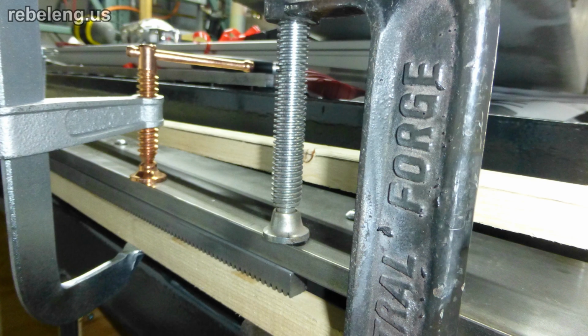I left the clamps on for about an hour to make sure that the adhesive on the tape had time to fully bond. Because of the large surface area, the bond on the rack is actually very strong. The foam in the tape also provides a slight bit of cushioning to the system. It has been 9 years and everything is still holding in place just fine.